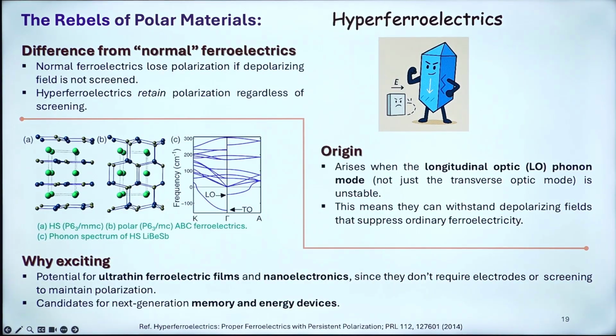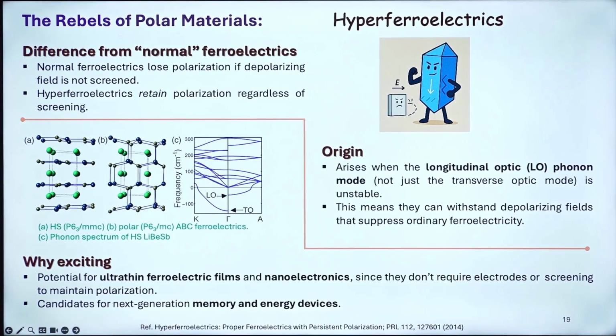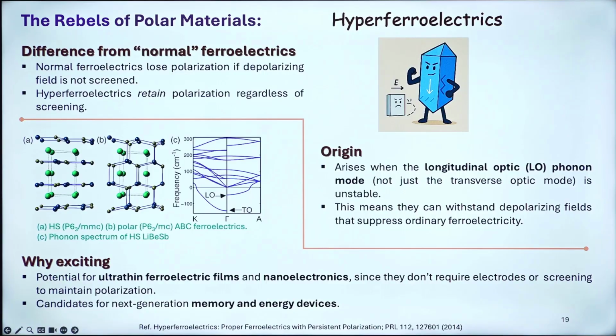So now we will try to see hyperferroelectrics. When the longitudinal optic phonon mode is unstable, this is more discussed in lithium beryllium antimony, where we do see along the k gamma direction it's completely coming down, and this is mainly the longitudinal optic phonon modes. Hyperferroelectrics are exciting because they can be used to make ultra thin ferroelectric films, which can be used for nanoelectronics and memory devices.